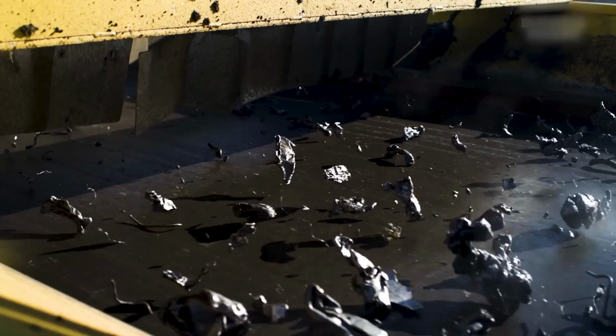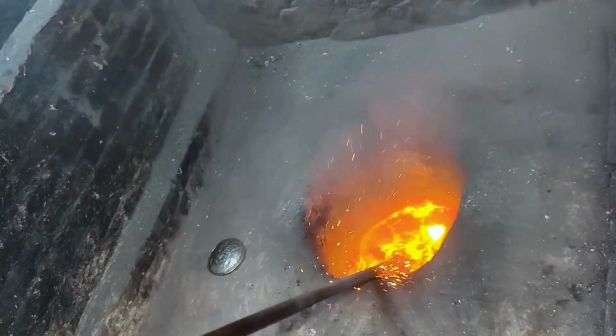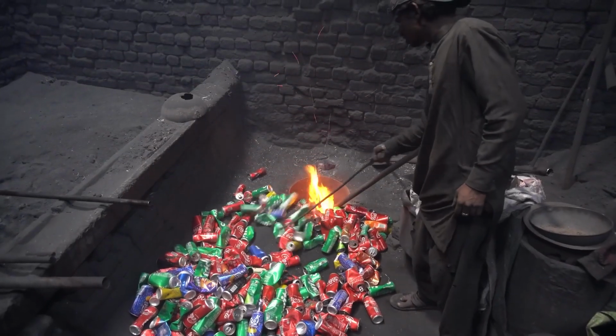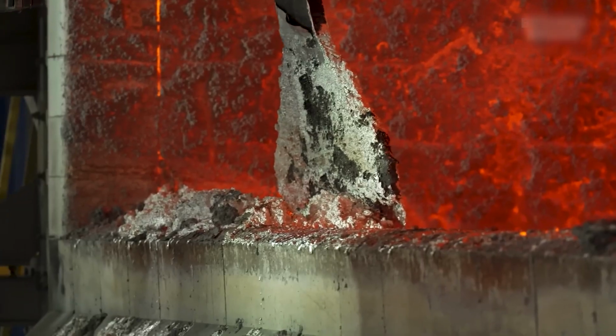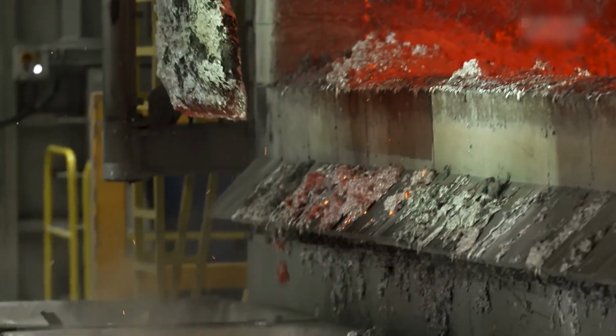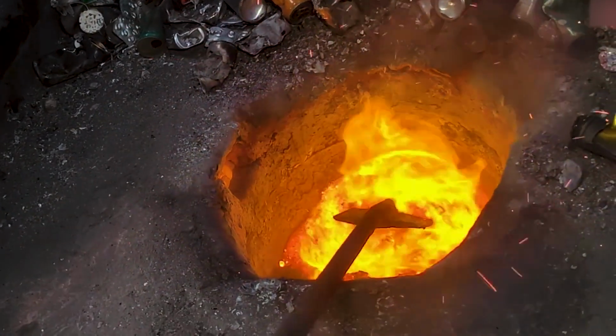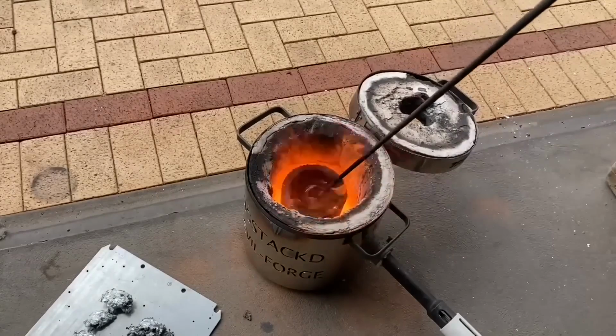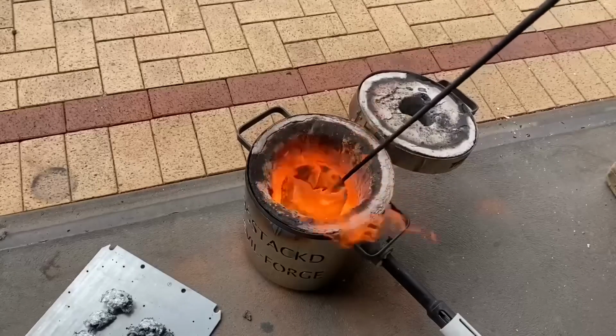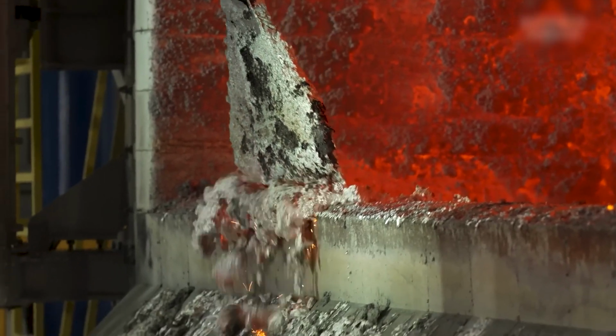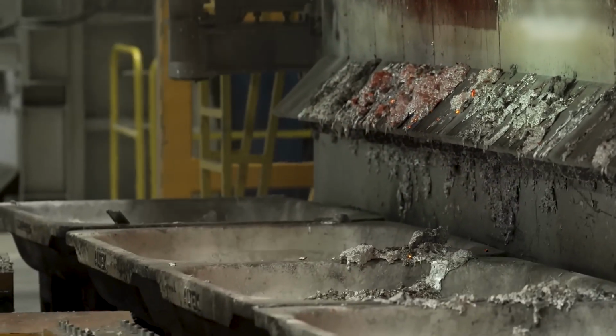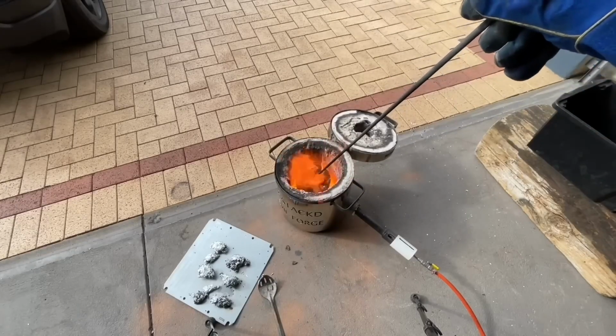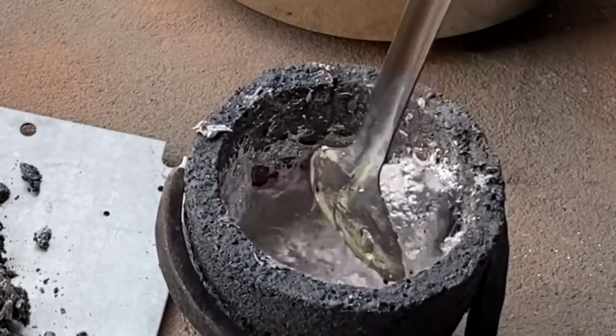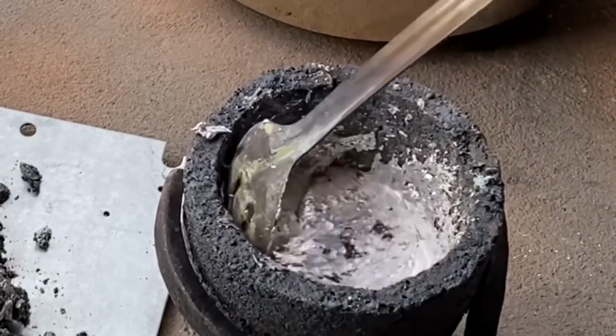With the coatings burned off, the clean aluminum pieces move to the next step: smelting. Inside massive furnaces, the metal is heated until it melts into a glowing, silvery liquid. But there's a problem. When aluminum melts, it reacts with oxygen in the air, creating a layer of aluminum oxide called dross. This dross floats on the surface, much like foam on a hot cup of coffee. If it's not removed, it can mix back into the liquid metal and ruin its quality. To deal with this, skilled operators use long steel paddles to skim the dross off the surface. It's a delicate job that takes both practice and precision. But that's not all. Modern recycling plants also add special chemicals called flux agents to the molten aluminum.